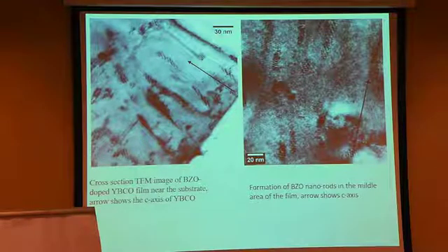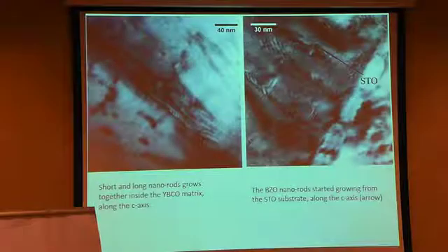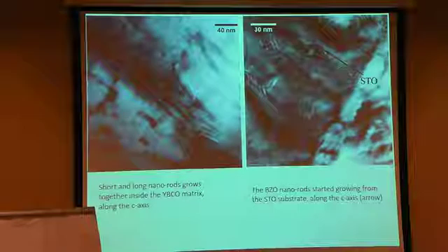So if you do not have other types of pinning centers, to have only vertically aligned C-axis columnar defects is not good. You see here, this pinning landscape provides a lot of different types of pinning centers, which is very good. I'm showing you a lot more images of these to see how important the pinning landscape is, and to have different types of pinning centers.